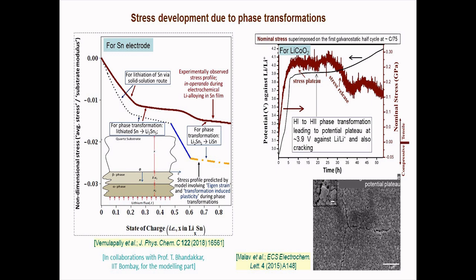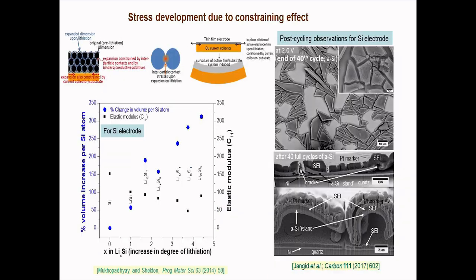Not just tin, but it's the same thing for lithium cobalt oxide, something which people had not looked into in detail, even though lithium cobalt oxide has been in use since 1991. So we saw that again during the phase transformation regime, which corresponds to the plateau, there is a stress instability and stress drop, signifying that there is fracture taking place during this stress plateau.